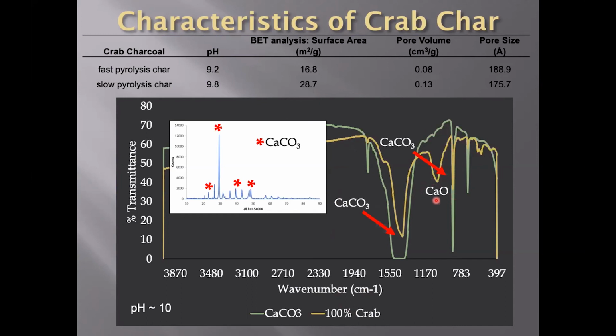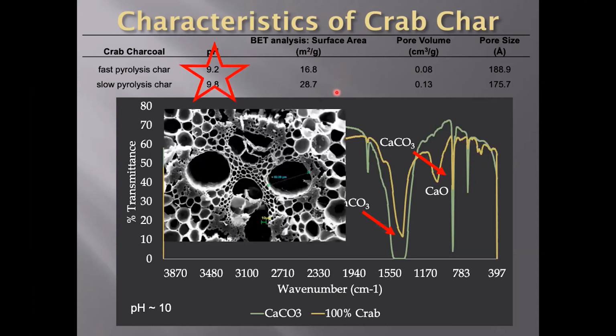But we also have this peak associated with calcium oxide, which is not terribly surprising because the pyrolysis, although it's a controlled temperature setting, you do get areas of very hot temperatures that go above your 450 degrees Celsius. And so that will facilitate the conversion of calcium carbonate to calcium oxide, but the concentration is fairly low. The crab biochar has an okay surface area, between 15 and 30 meters squared per gram, and some limited porosity. So this is a SEM image of the crab biochar in an area that we found to be quite porous. This is most likely due to the organic components of the crab waste that is left within the shell. But because of this porosity and this reasonable surface area and the basic nature of the material, we thought it might be useful to look at this crab biochar as a possible remediation material.